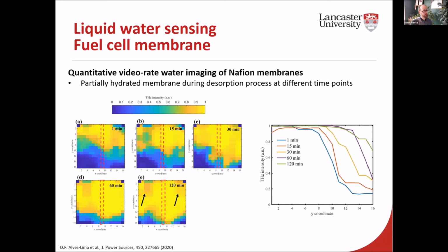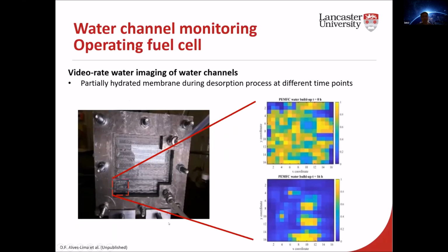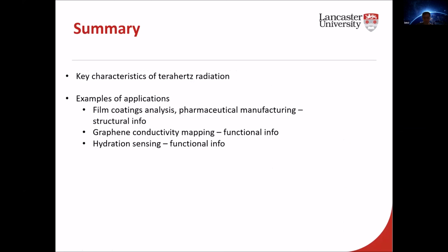Yeah, sure. So these terahertz images just basically show areas of dryness versus areas of wetness. And what you can see is that over time, wet areas get replaced with areas of dryness. Obviously now what we're doing is extending this further to an actual hydrogen-based fuel cell in operation, whereby we can start seeing the buildup of water in water channels. So this is the very beginning of a process and the very end. Again, this is very early work in progress.